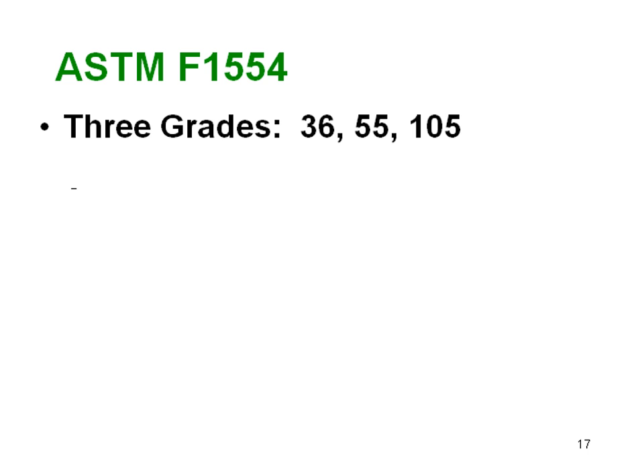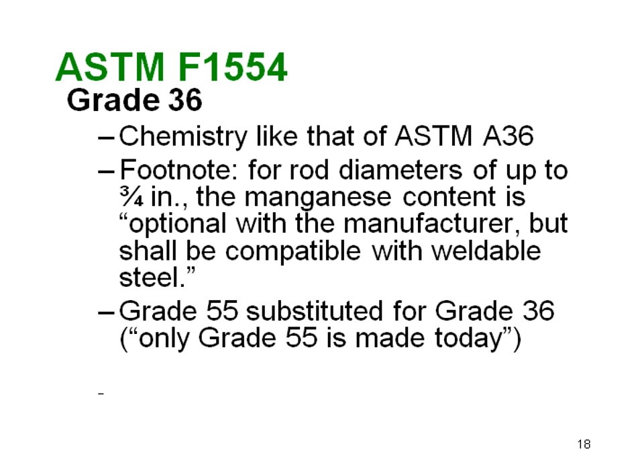When you look at 1554, you'll find that there are 3 different grades of anchor listed, grade 36, grade 55, and grade 105. Now, grade 36 has a name that kind of implies it would be like A36. And indeed, if you look at the chemistry in 1554 grade 36, it's very much like A36 steel. And you, of course, know A36 is a highly weldable material, and so you would tend to have a lot of confidence when you looked at grade 36.